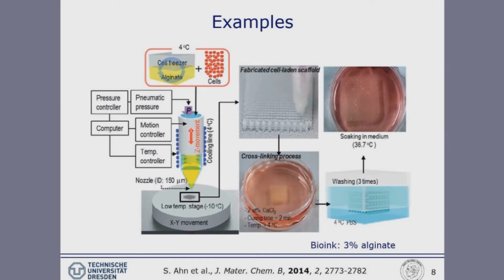Therefore, the team has been able to demonstrate that they can print with a low-concentrated, only 3% alginate hydrogel, very defined three-dimensional macroporous constructs, which then in the next step are cross-linked in a calcium chloride solution, again cooled to +4 degrees Celsius for 2 minutes. And then after a washing step, the cell-laden construct is put in the incubator. So this works well.